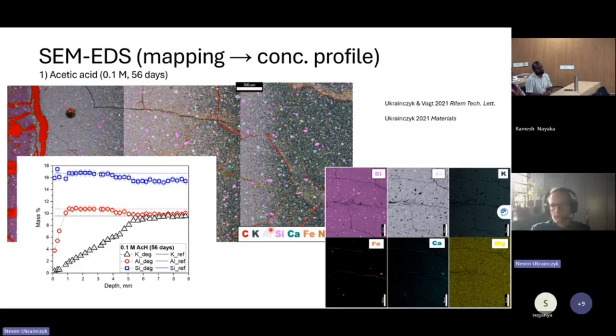But to go all the way to the other alkali activated system with a lot of calcium, then you have less activators. You are correct. But then you are more in cementitious systems because you have basically calcium alkali silicate hydrates, C-(N)-A-S-H. And in the geopolymer, you have more of this 3D connected, fully polymerized network. Then Davidovits says that alkali activated materials, although he doesn't like the term, are basically just cementitious material with more alkalis in it.